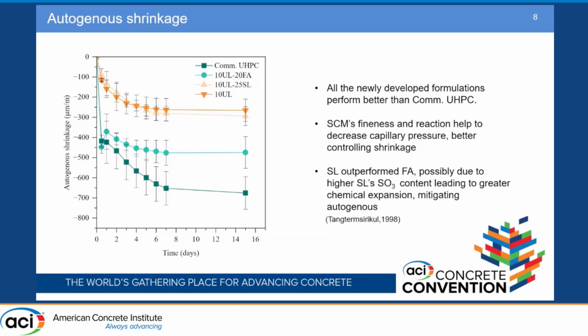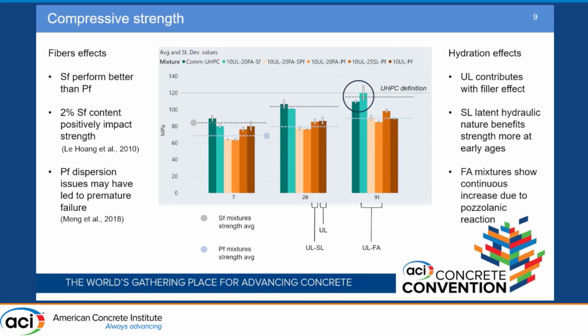Also, it was interesting to see that slag performed better than fly ash, and this was because of the sulfur trioxide (SO3) content that was higher in the slag, and then its chemical expansion helped to offset part and mitigate the effect of the shrinkage. Of course, we evaluated the compressive strength of these mixtures up to 91 days. And we saw clearly two effects among the formulations that we developed.